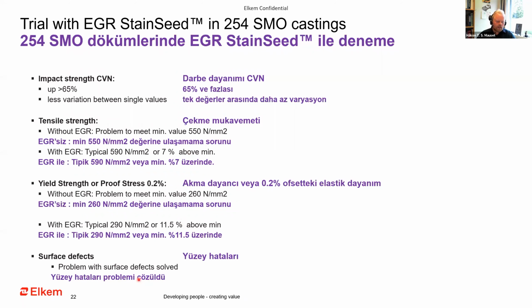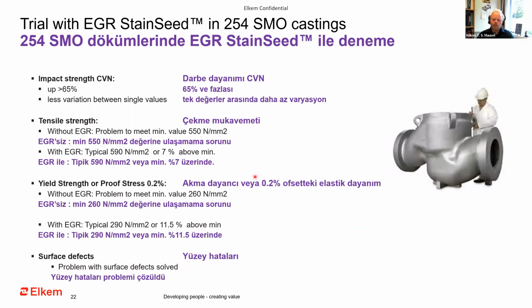And as I mentioned, they had a lot of surface defects, which they needed to grind and weld on, but the problem disappeared when they started to use EGR. So I think they didn't have any weld repair connected to the surface anymore. So this is not the exact component, but this is a typical valve body.